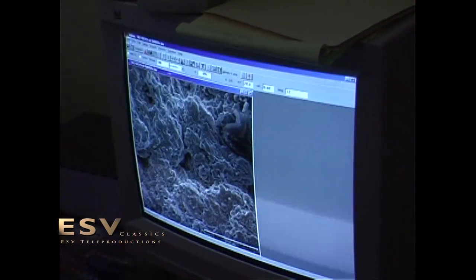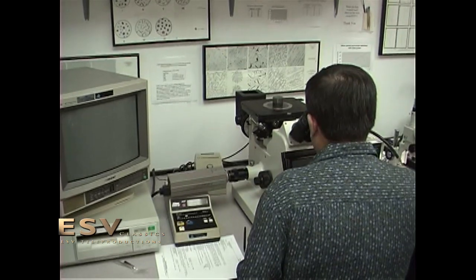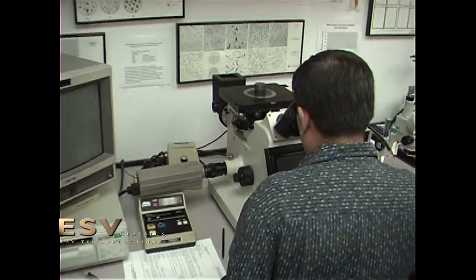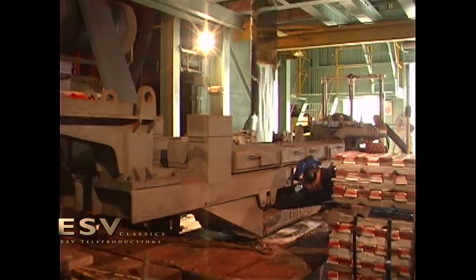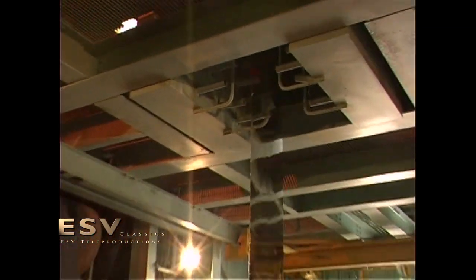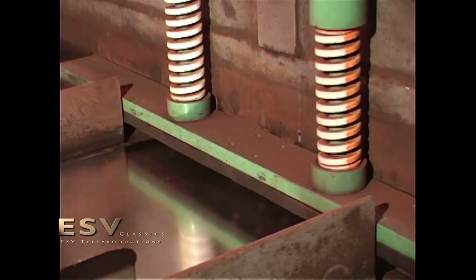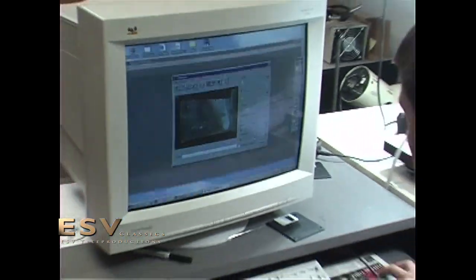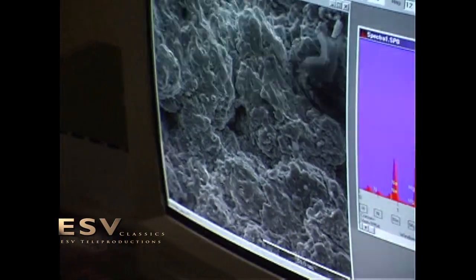After nearly five years, with literally hundreds of alloy tests and considerable metallurgic analysis, Tern Two was born. Tern Two sports the patented Follensby ZT alloy coating, a combination of zinc and tin which not only satisfies the most stringent environmental demands, but also substantially surpasses the original terne lead-tin coated product in performance. In fact, the hot dip process application of ZT alloy on carbon steel is projected by independent studies to outlast antiquated galvanized steel by a factor of 15 to 1.